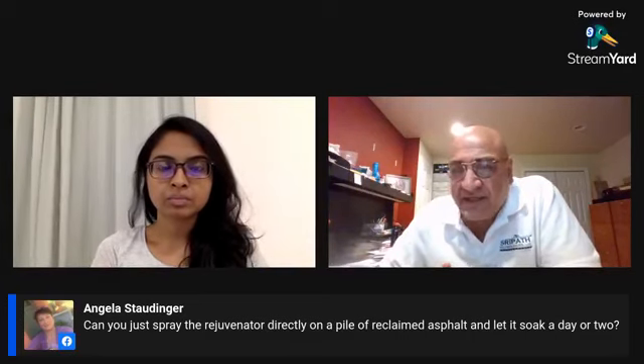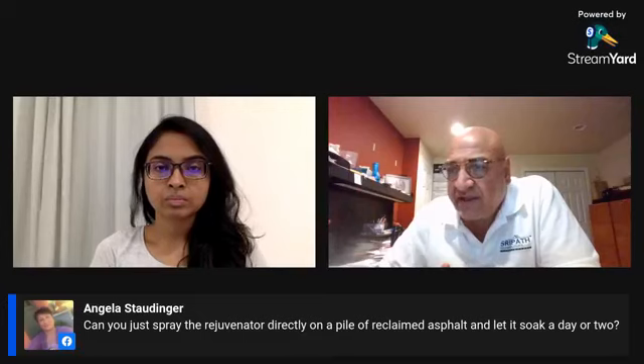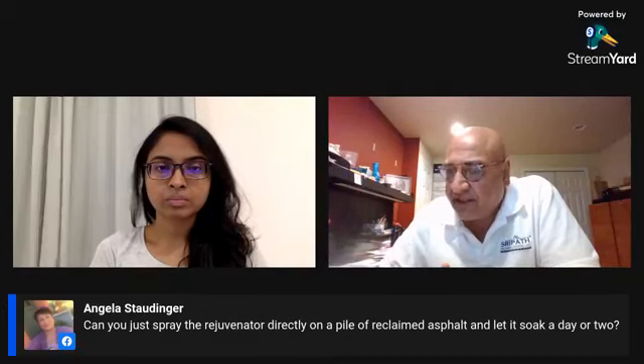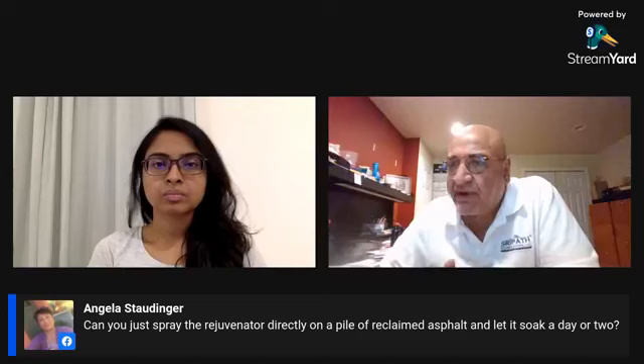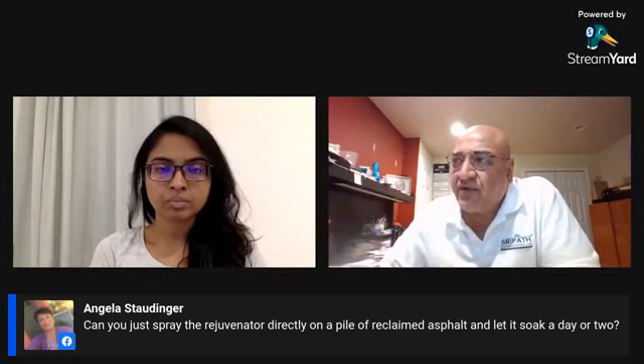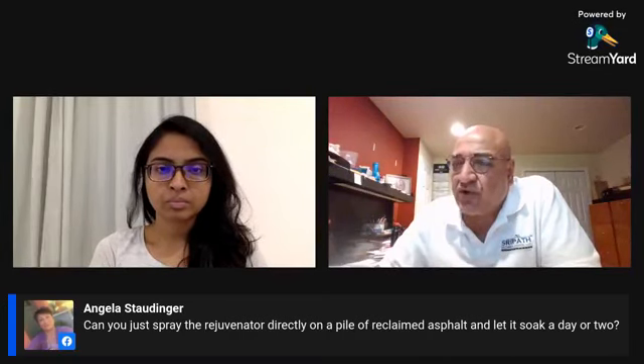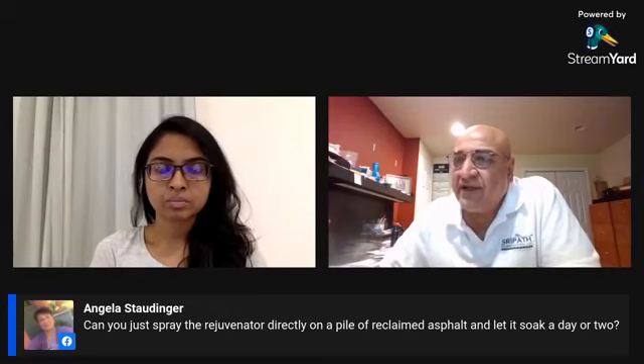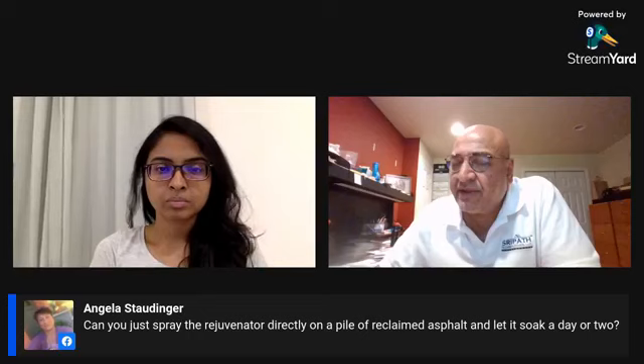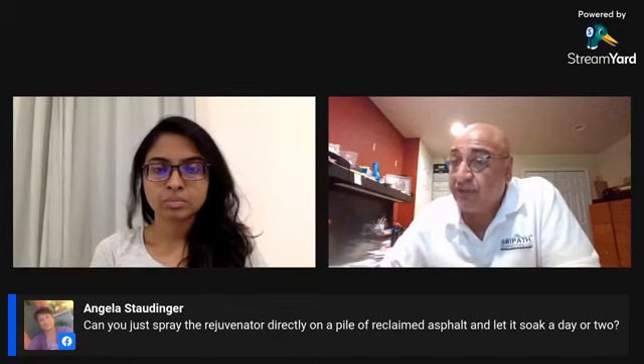And it turns out it's a good idea in theory, but not so good in practice. And here's the reason why. Remember, when you spray your Rejuvenator on a RAP pile, you're softening that binder. It's penetrating into that aged RAP bitumen. It's softening it. It's rejuvenating it. And now, remember also that you're adding 40% of this into your mix, so you've got to heat it.